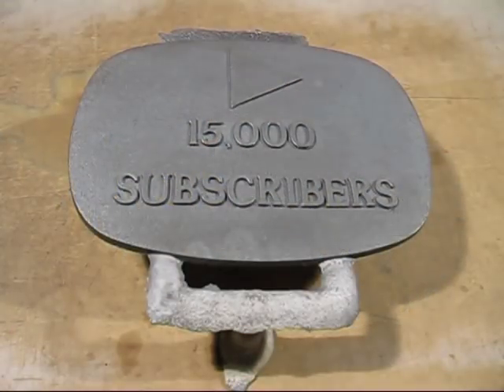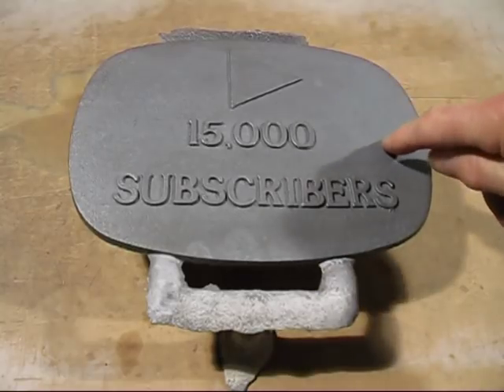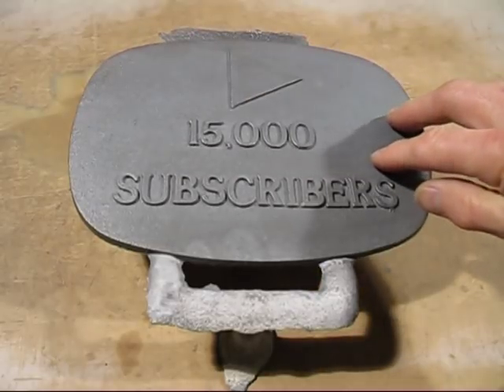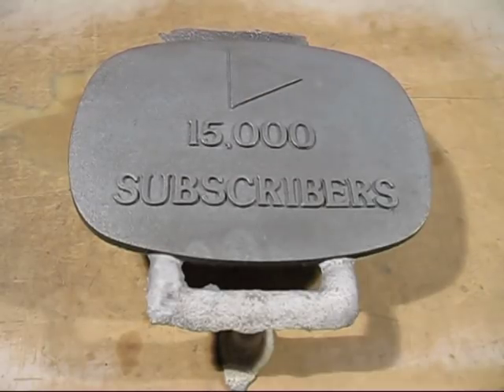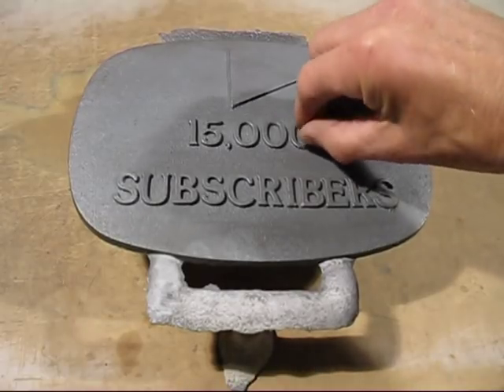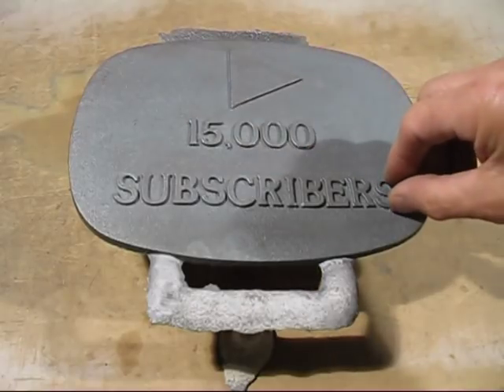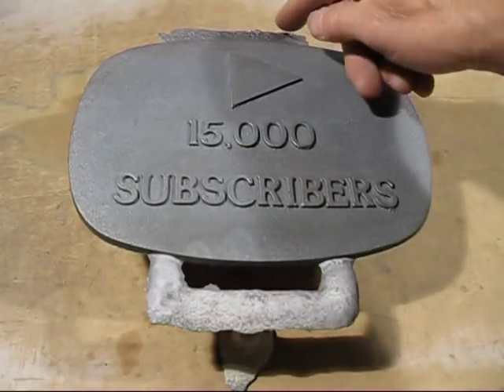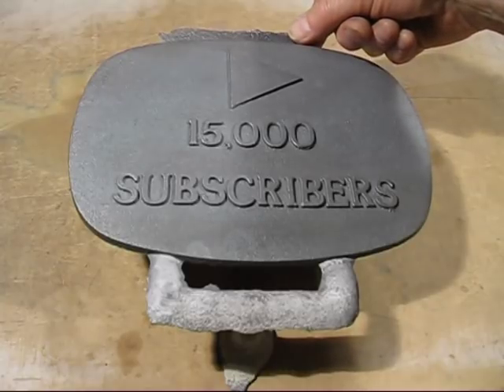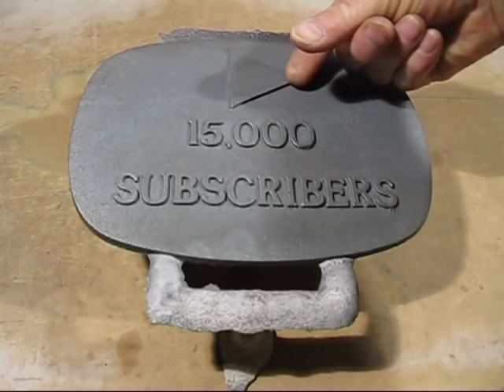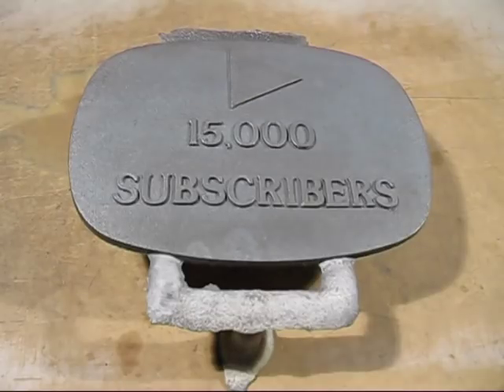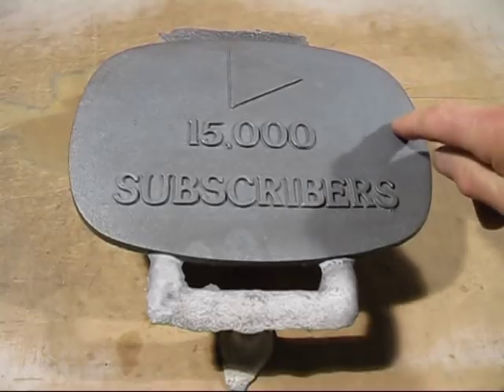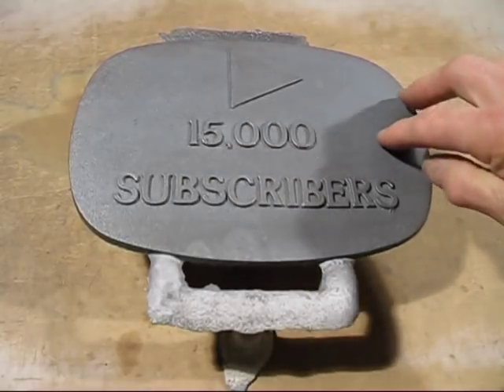This is the second mould I poured, and I used coal dust in the facing sand. Now what happens with plaques like this is it's got a large surface area. You have to ram it very softly, and if you don't ram them softly you'll get expansion defects. But one of the problems of ramming them softly is you can see around the letters there that I didn't quite ram it enough, and the same with here. But also the other problem is just this area here, it was too softly rammed and the mould opened up a little bit. But overall it came out with a soft, nice, even surface finish over the cast surface there.